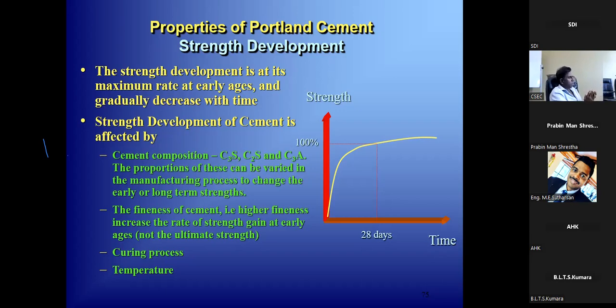Now I'm getting towards this low carbon concrete, where we need to be smarter, using these newer things, not just throwing some materials and making it low carbon, but trying to optimize the structure as well. So optimizing the structure, use some high strength, high performance concrete, as well as some smarter techniques, because we have to understand it'll be occupied only after, let's say, 1 year or whatever. Use a bit higher strength, but you need to get the approval from the clients and the certifiers. But you can, so that's why you need enough knowledge for that. You can easily use 56 days now. I just tell people use 56 days, because you will have some strength increase, right? And rather than putting 28 days in the drawings.